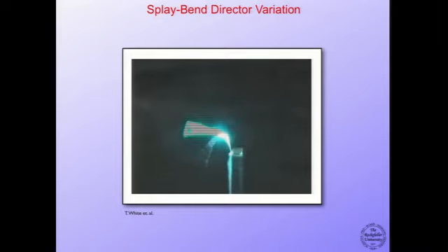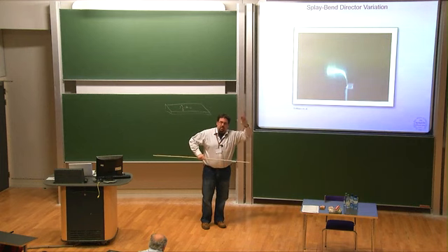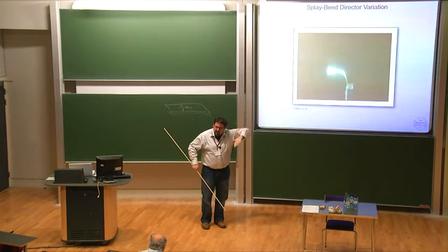So here you have a much, much stronger light source, and you get this flapping effect. The flapping is higher order because you're getting occlusion of the light source by the end of the bender. It bends strongly, and it bends so strongly that it blocks the light from the front edge. And then when it blocks the light, it goes into recovery, and then it's open again to be bent. So it does this.